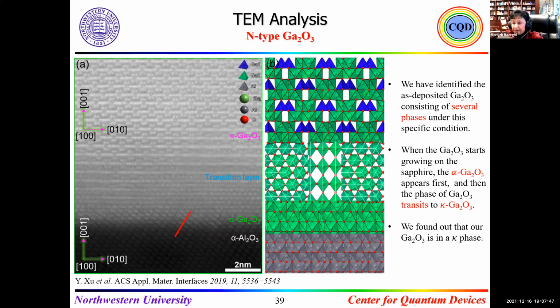We increase, we do annealing under hydrogen again, and over the course that we do, up to 1000, it becomes beta. We decrease the temperature and grow again in exactly the same condition, and we have kappa. X-ray beautifully shows that we have kappa and beta together, one on top of the other.